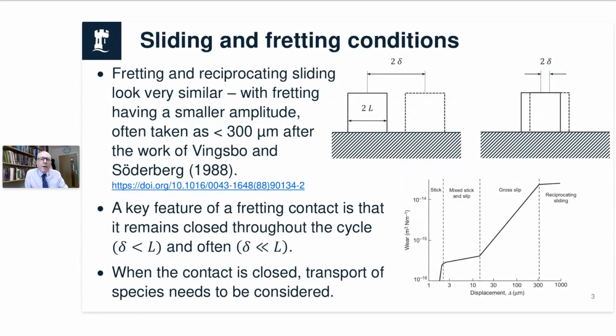Okay, so we start off with that sense of fretting. What is fretting? We all probably know that fretting is small amplitude sliding, and many of you will recognize the chart in the bottom right-hand corner of this slide, which comes from the work of Vingsbo and Soderberg in 1988, showing how the wear rate varies with the displacement amplitude. Down at the left-hand side, it's stuck. Then it moves through a mixed stick-slip regime, where there is fretting probably at the edge of the contact. Then it moves through what they term gross slip, where the whole contact is moving, but probably not moving very far. They've given their displacement amplitudes there, as you can see. They went up to about 300 micrometers, and said that once it goes above about 300 microns, we're going to call that sliding.